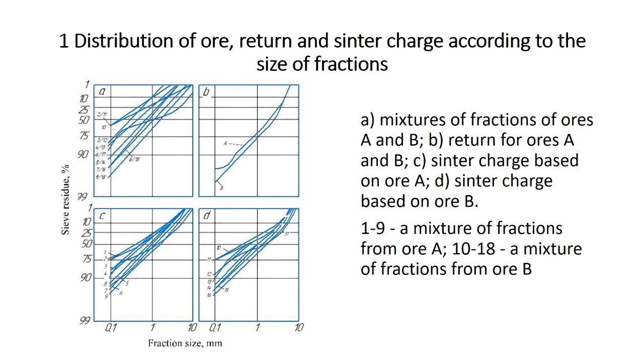When evaluating the research results, it turned out that the return size fluctuated greatly. For each ore, based on sieve analyses of the return, a mix analysis was calculated, which is graphically presented in Figure 1b. It was found that the return during sintering of hematite ore B has fewer fine fractions than the return during sintering of magnetite ore A.